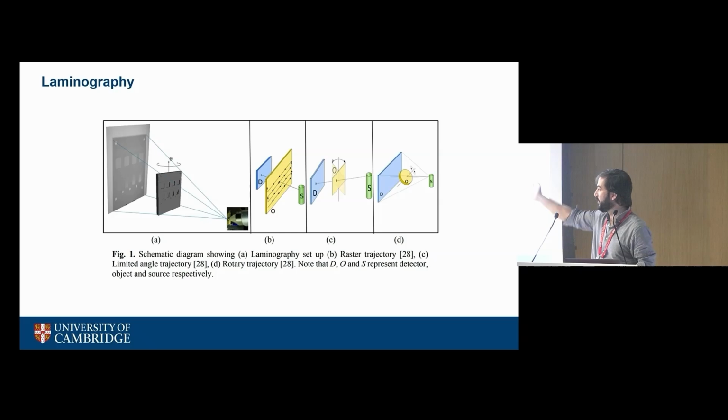So you need some weird geometry when you move the sample around, rotate it a bit, and whatever. You can never do 90 degrees. And this is very common for composite materials. Generally you have a big panel or something, right? And so it's something that industry is really, really interested in. And what happens is that your standard algorithm generally just fails miserably trying to reconstruct this, right?